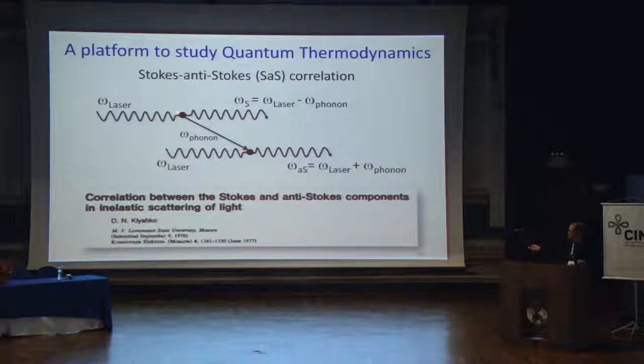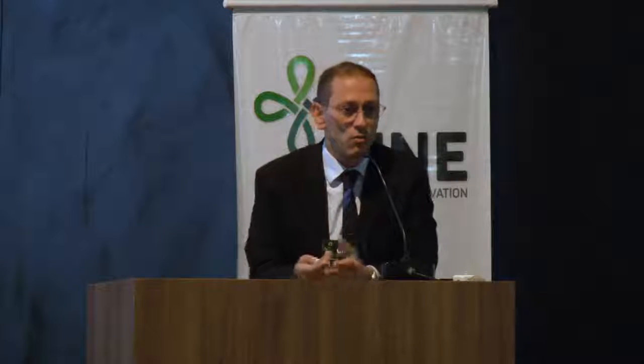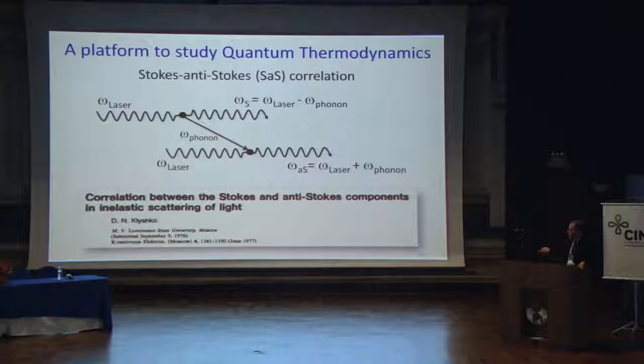So this is a process where the same phonon that is created in one process is annihilated here. And when you do this kind of thing, you generate correlated photons. And these photons are correlated with some vibrational information inside the material. And the point, and this is the reason why I bring this here, is that this places us in the condition to study quantum thermodynamics. From the point of view of quantum mechanics, there is a lot of information that you can also transform into energy that is lost when you lose the quantum limits and you go to the classical life, okay? So we are studying the thermodynamics of these effects, of this correlation between photon and material, to understand quantum thermodynamics.